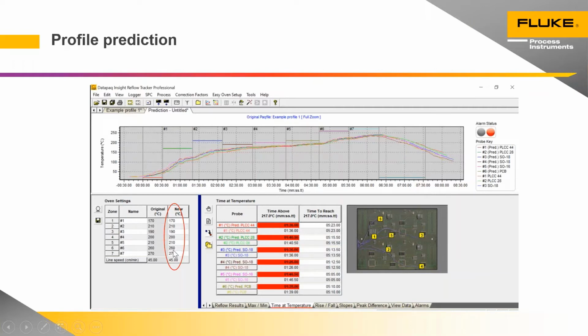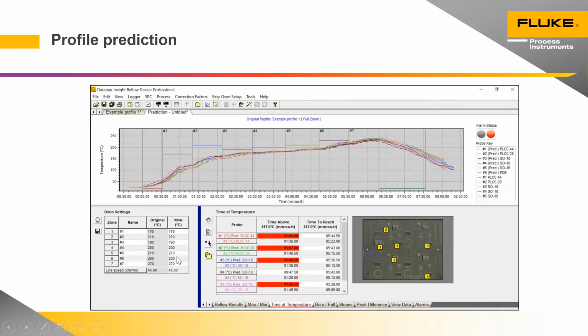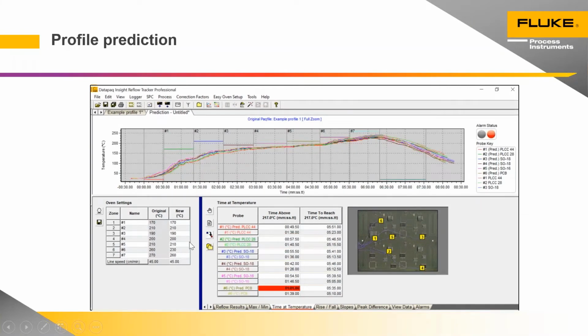I do now have the option to type in some new oven settings here, so I can try some what-if scenarios. What happens if I change this temperature on zone 6 to 230? At 230 degrees, the software is predicting that I will have reduced my time above liquidus quite dramatically, and some of the heavier components are now within specification, but I'm still getting these alarm values on my predicted profile. So I can try again. I try another setting, maybe this time I'll reduce the 270 down to 260. The software is now predicting that only one of them is out of specification, and in fact it's only out by 1 second. So you can see this is as if you have a virtual offline oven.